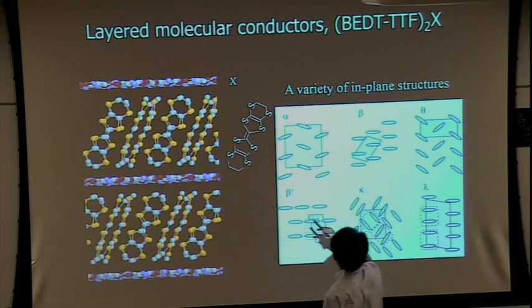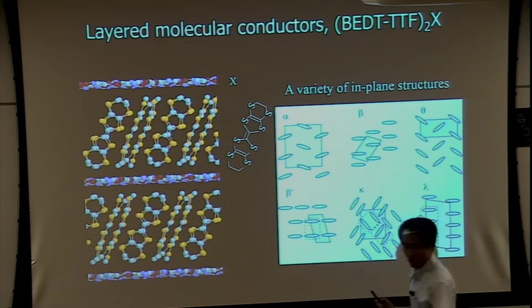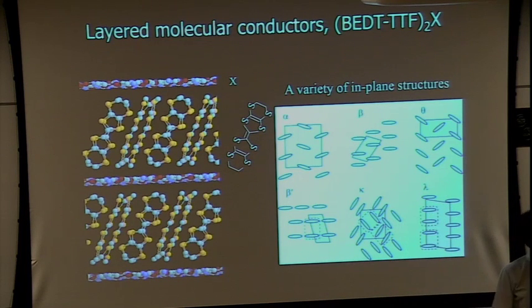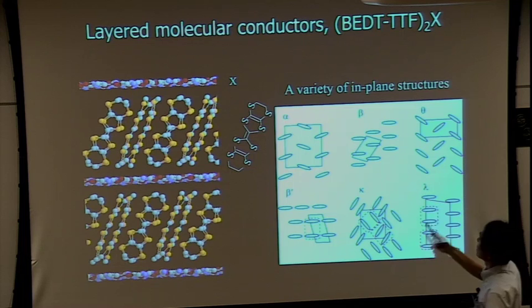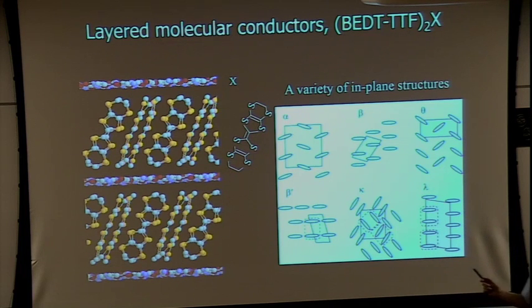This X plays the role of the insulating block layer, like the block layer in the high-Tc cuprates, the insulating layers. There are many kinds of molecular species as X. It's one monolayer, insulating and non-magnetic - just a spacer.